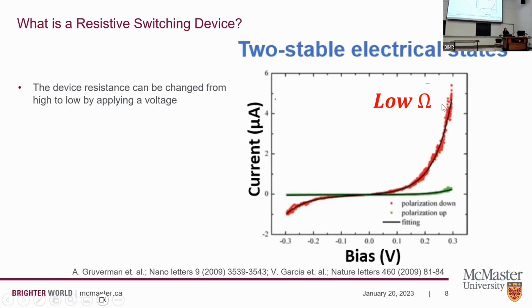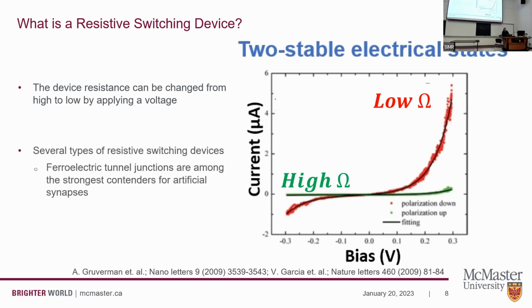This red curve indicates that we have a low resistance, also known as the low resistance state, where the current is able to flow. The green curve corresponds to a high resistance state, because the resistance in the material is so high that no current or almost no current can go through. Several types of resistive switching devices have been fabricated and reported, but among them, ferroelectric tunnel junctions have been identified as the strongest contenders for artificial synapses.